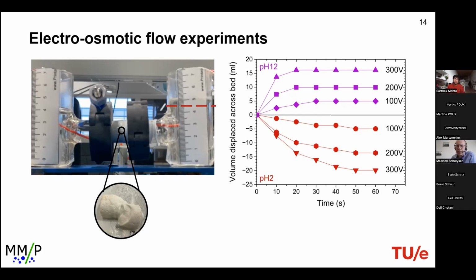The interesting thing about this is that we are not limited by the area. So as long as the electrode area to the area of your sludge is maintained, you can go to 1 meter square, 100 meters square, your dewatering rate will stay the same. So in order to increase the capacity of dewatering, I would say we expand on the area while keeping the potential and the rest of the conditions same. So we can dewater at a faster rate, meeting the industrial requirements. While the process might be slow, by increasing the area, we can meet the industrial demand still.